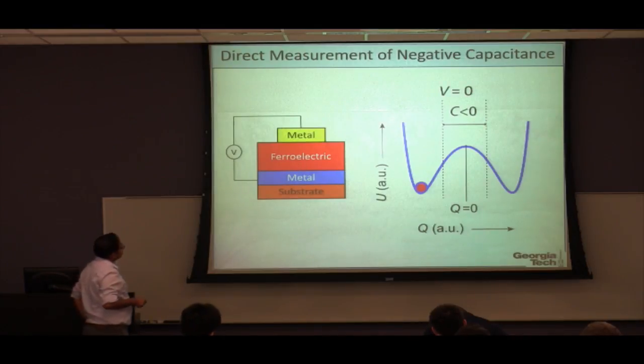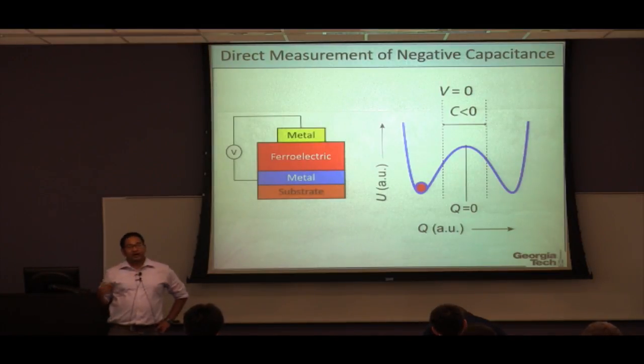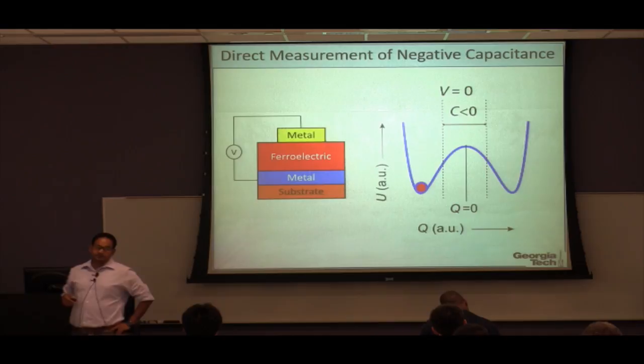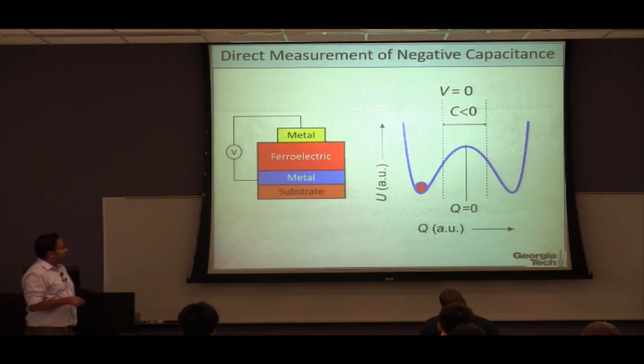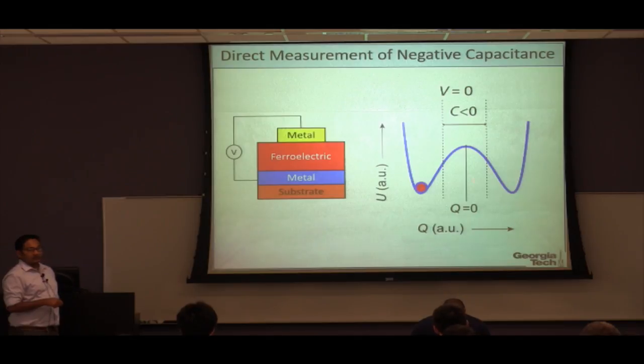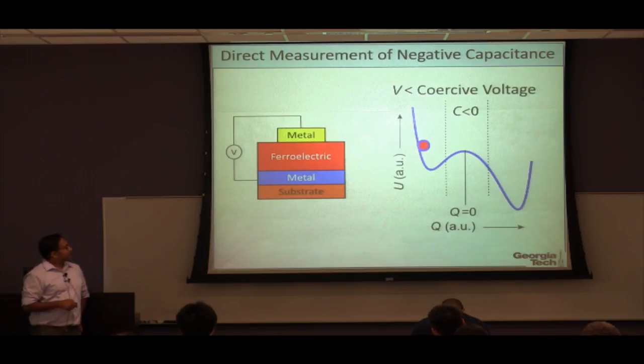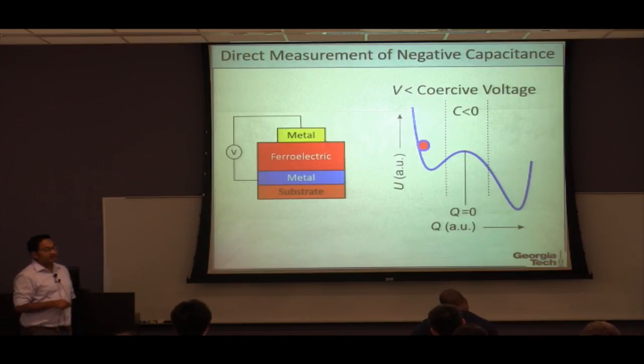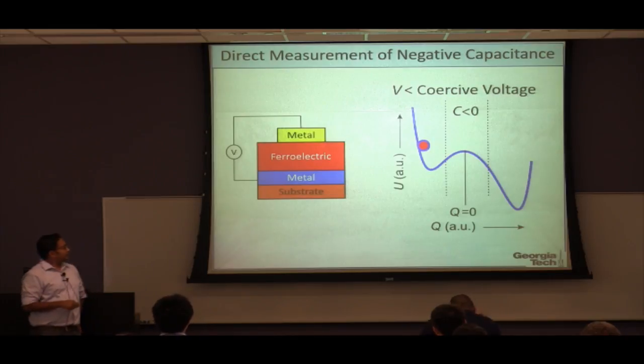All right. So let's first look at how we measure negative capacitance directly. Again, we go back to this energy landscape picture, and we start from a certain polarization point here, which is stable. Now, if we apply a voltage which is smaller than the coercive voltage, what we will see is that the energy landscape has tilted, but there is still a barrier.